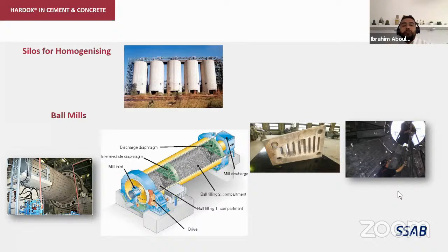Then finally, we have the last grinding step, which is the ball mill. The ball mill is relined with more or less castings, but the castings cause a lot of problems. The weight is very high, which requires a lot of power, which is a lot of money, as well as the noise of that is very high and it's not allowed in many places. The solution for that is that we use Hardox 500, 600 embedded into rubber to decrease the weight and to improve the impact toughness using the rubber's ability for that, and it performs much better than the castings.